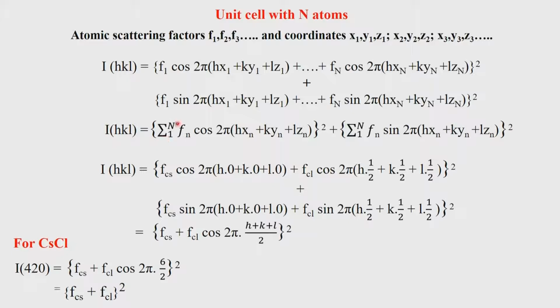Since we have the intensities available with us, we can use these intensities and then determine the structure factors. The major problem which comes up there is the phase problem. We get the magnitude of f of HKL, we do not get the alpha associated with HKL.